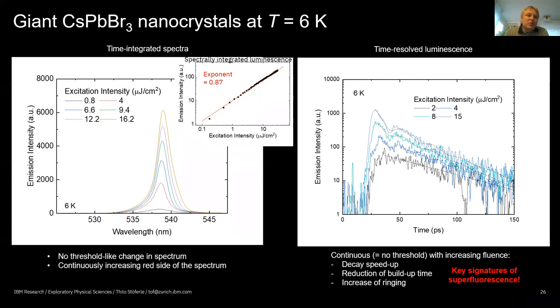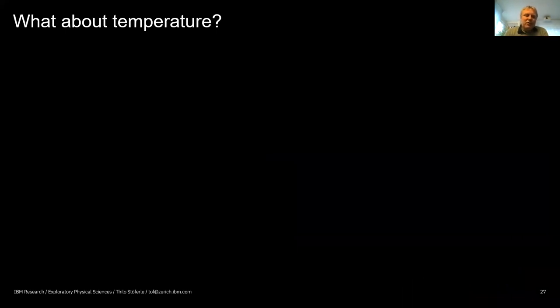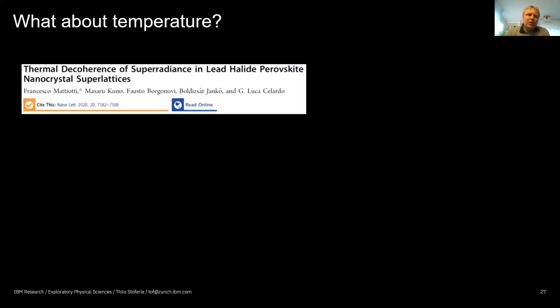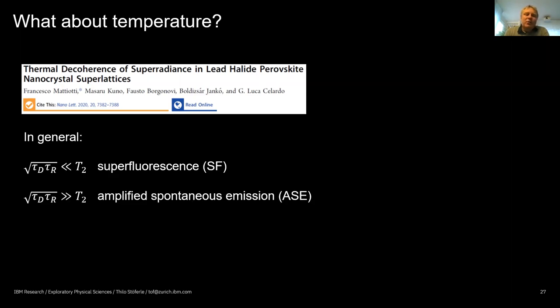This answers the question: superfluorescence occurs even in bulk-like material — so even if quantum dots had merged, similar signatures would be observed. The next question is temperature: all experiments so far were at 6 K. Some theorists calculated that in our system, thermal decoherence limits the speedup we observe — only 28x, whereas with millions of coupled quantum dots one would expect a much larger superradiant effect. There is a basic relationship: the geometric average of the delay time and superfluorescent decay time should be faster than the T2 time of individual quantum dots.